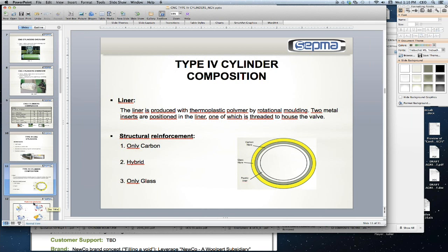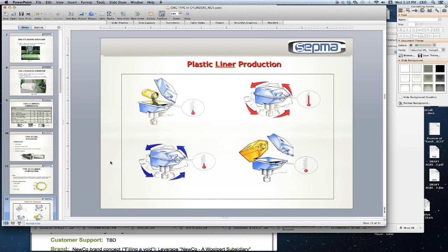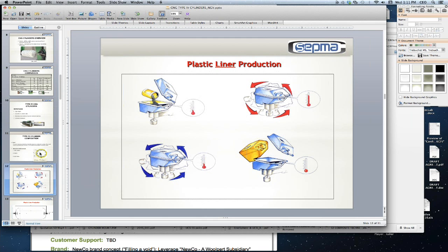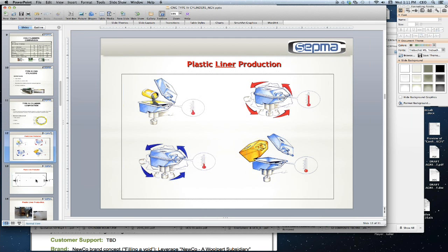Let's see how we can manufacture the plastic liners. So plastic liner production is typically done with a technique known as rotor molding. Rotor molding is a very common technique in the thermoplastic industry. You can see you start off from a powder, which is then placed in a mold, the mold is then closed, and then we go to the right-hand side where you start applying heat and rotation. That guarantees that the powder is projected towards the walls of the mold, and the heat guarantees that the plastic starts melting. Then, while spinning, you start cooling it down, and at the end of the process, the bottom right, you have your part. This is a very common technique and the one primarily used by most producers out there.